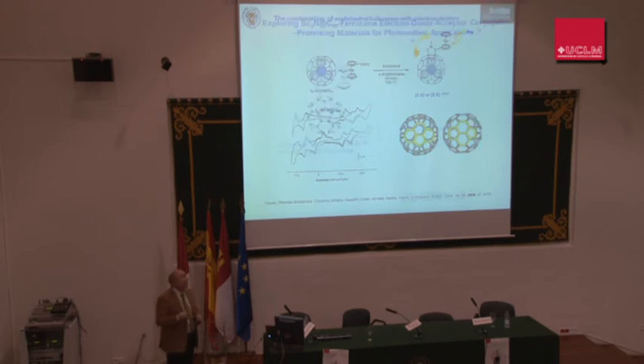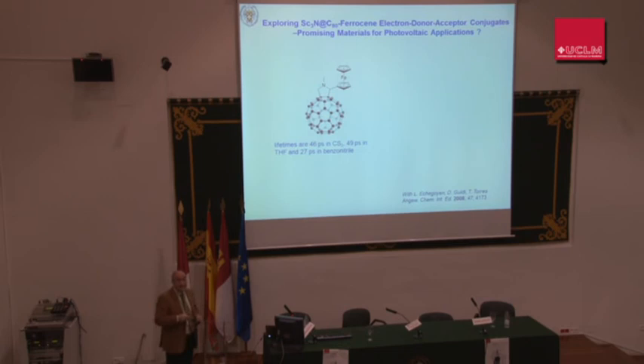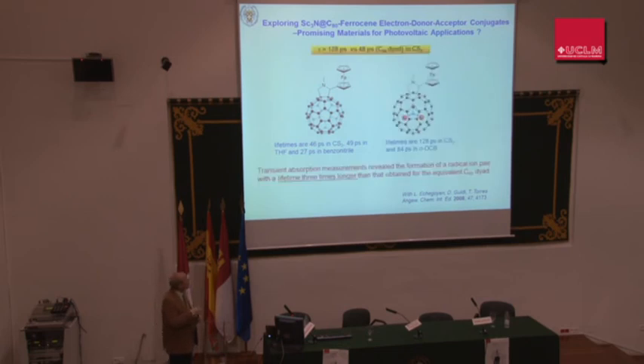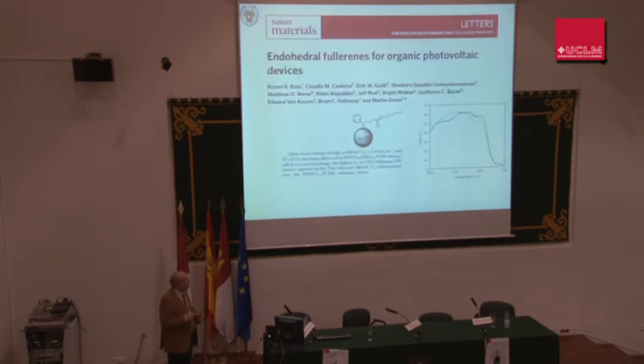How efficiently? Well, if we compare with the pristine C60, what is remarkable is that the transient absorption measurements reveal that the radical ion pair was formed here with a lifetime 3 times higher than pristine C60. So in principle, this system could be quite appealing for a photovoltaic approach. And this was reported in 2008, and just 1 year later, in